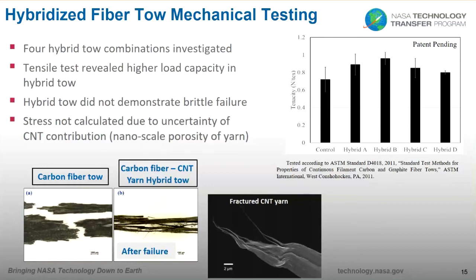But one thing that I do want to point out is that we often report the tensile data for samples containing nanotube yarns in tenacity, which is in newtons per tex. One of the reasons why we do this is because the carbon nanotube yarns do not have a perfectly cylindrical geometry. And the nanotube yarns are also porous, so it is not a straightforward process to calculate mechanical stress like you would for normal conventional fibers. So to normalize the properties of the tow, we use tex, which is in grams per kilometer. So I just wanted to point that out.